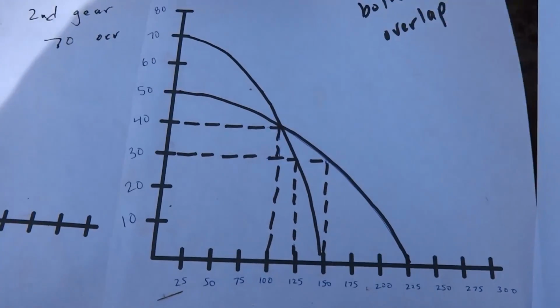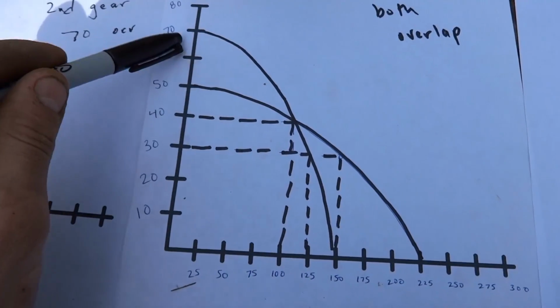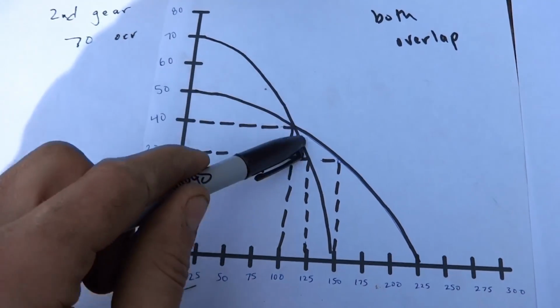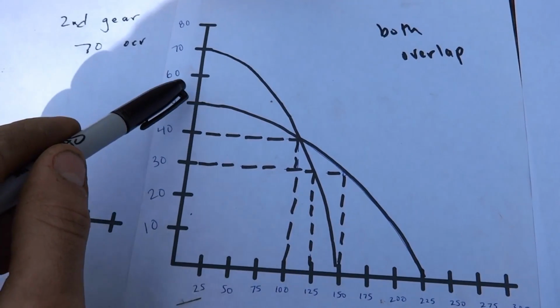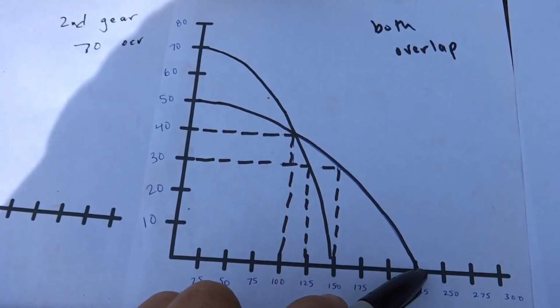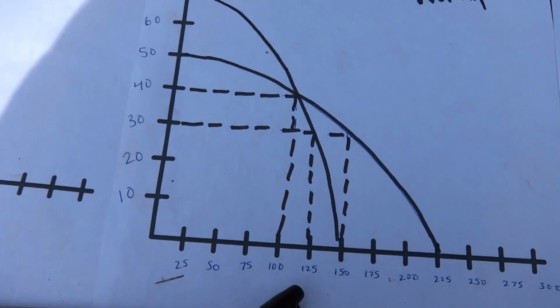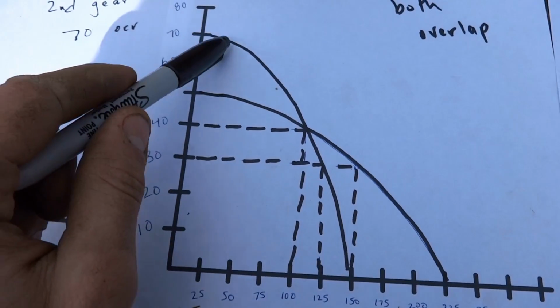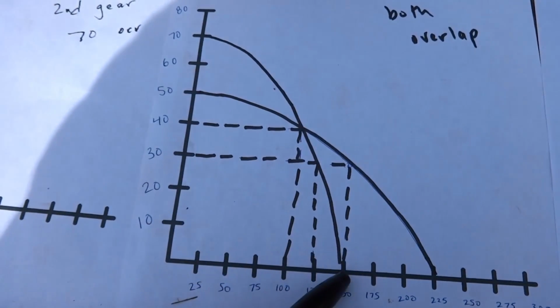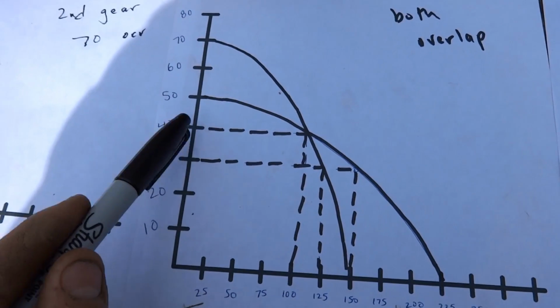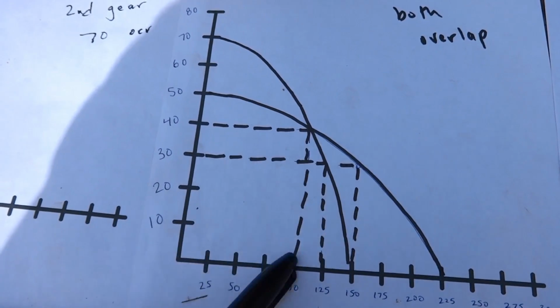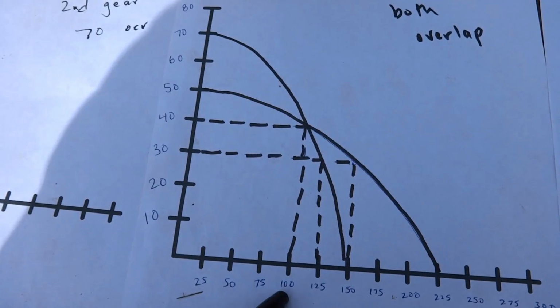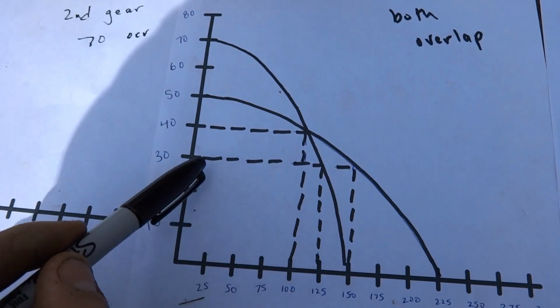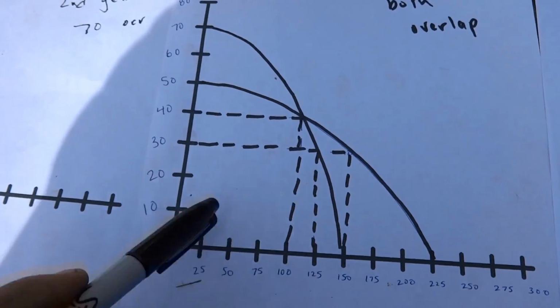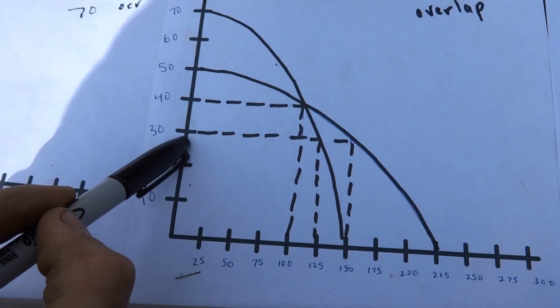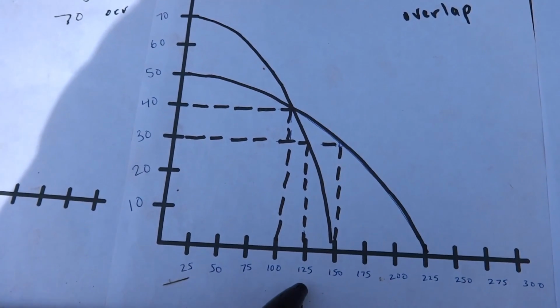This is the overlapping of the two. This is low amperage, high voltage, and this is high amperage, low voltage. As you can see here on the low amperage, high voltage chart, a normal arc, which gives arc length, has a voltage of 40 and the amperage of 100. You hold a tight arc, voltage drops off to 30, and amperage goes up to 125.